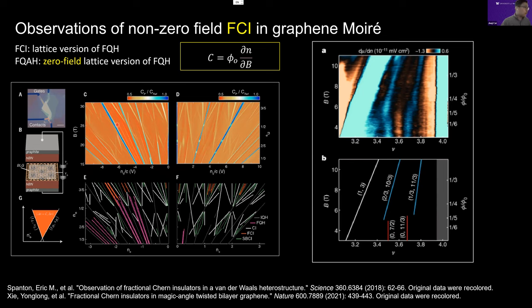So as long as you see a blue curve, it's actually an incompressible state. And the carrier density where the incompressible state happens shifts linearly with respect to increasing magnetic field. The slope of this shift is quantized according to the theory, and experimentally you can extract it, and it's actually quantized. Using this method, people can get topological information of those systems by extracting the slope of the so-called Streda formula.